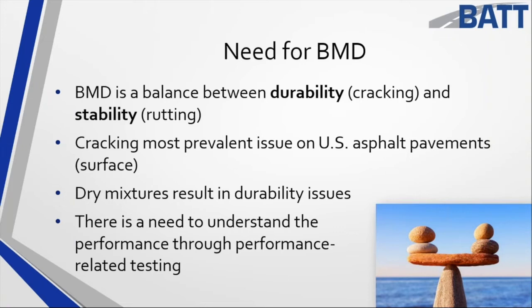As I add that asphalt, I've got to do something with it — it's going to lower my voids. You've got to work with the DOT to understand, when they talk about balanced mix design, are they going to lock you in at four percent air voids, or are they going to allow the air voids to be somewhere between three and four percent? I don't mind designing down to two percent, but I know that not everybody has that risk profile. Natural sand can really bite you as you go to lower air voids, though it can also aid in compaction when used properly.